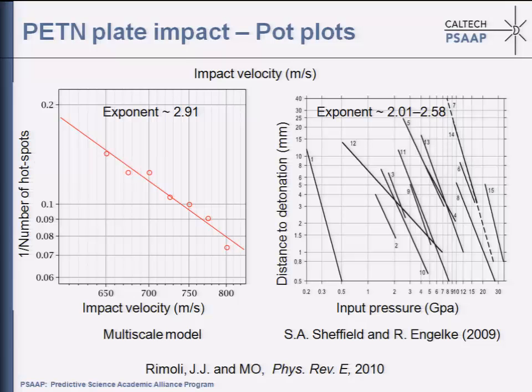To make contact with engineering test data, you really have to go all the way to the macro scale. So these are some typical results from tests that would be conducted, for instance, at the Army Research Lab. And typically what they do is they plot in a logarithmic scale. This is what is known as a plot of the impact pressure versus the distance to detonation. And they find that there is this power law relation.